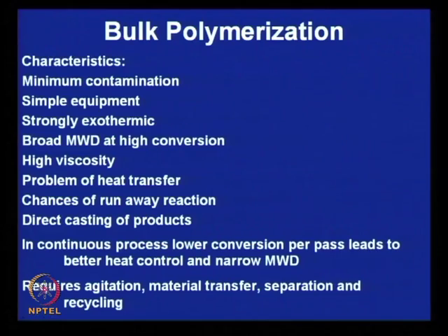In order to avoid that high viscosity increase in a big reactor, a pre-polymer of lower conversion is made, and that pre-polymer is used for direct fabrication of product.